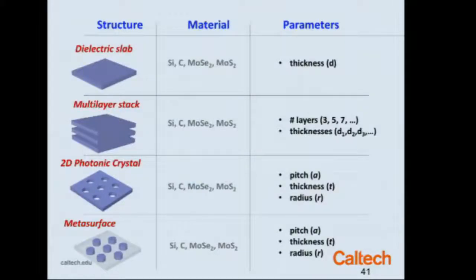So these are the structures that we're going to look at. We're going to look at dielectric slabs, just a uniform thickness, homogeneous dielectric slab, just a sheet of material, a multi-layer stack. So imagine you had high index sheets with low index sheets of a material like aerogel between them, and up to maybe 7 layers. A so-called 2D photonic crystal. This is a motif that's familiar to optoelectronics people. We can make structures that exhibit guided modes and band gaps within the plane using a film that has a periodic array of holes. This gives rise to Bloch-like modes for light, periodic modes for light inside the film.